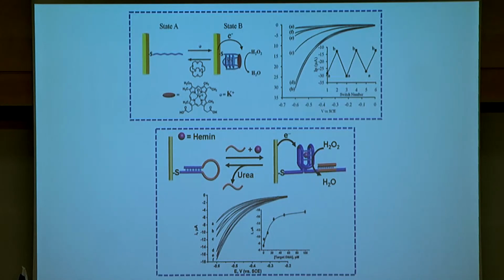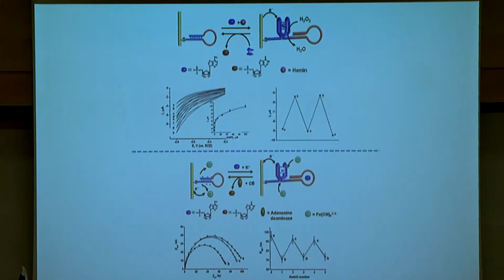But once we have this, we can basically develop a whole series of functionalized electrodes that can act for sensing applications. For example, you can take a hairpin structure of nucleic acid that includes a recognition sequence for genes, microRNA, and other nucleic acids. And in the stem region, the blue part, we encode the information of a G quadruplex. Once we open this hairpin structure, we generate the G quadruplex, which incorporates the hemin, and the electrocatalyzed reduction of hydrogen peroxide provides a signal to read out the sensing process and to amplify the sensing event of the respective gene or microRNA. This concept was extended to several other analytes.